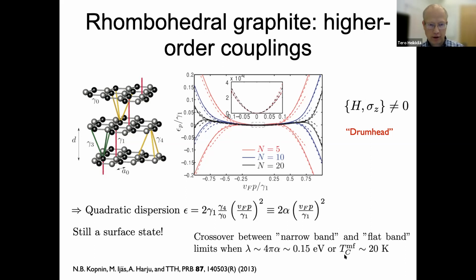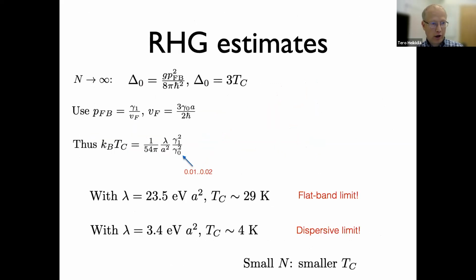Basically, the statement is that if the mean field TC is larger than 20 Kelvin, then we are completely in the flat band regime. If it's a bit less than 20 Kelvin, you cannot do a Fermi surface approximation, and you have to go much below that in any case. You can make estimates with the coupling strength values that I gave earlier. If you take the larger coupling, you get a TC of almost 30 Kelvin. If you take the smaller coupling provided in the literature, you get maybe 4 Kelvin.